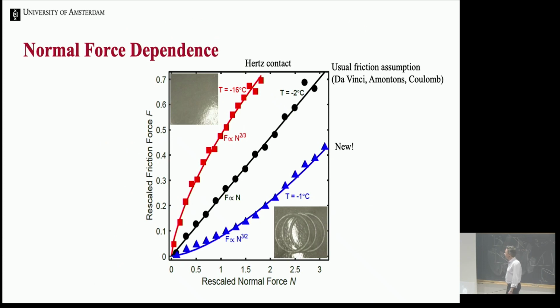And we can infer a lot of things from just looking at the ice surface. So if we're at very low temperatures and we do the experiment and we look at the ice, it is as if nothing has happened. If we are very close to melting, we actually make a track in the ice. The ice has become so soft that we actually leave a trace of the little particle, which is my ice skate. And this is what I told you. If we want to do a new experiment, we simply displace the rheometer by a couple of millimeters.